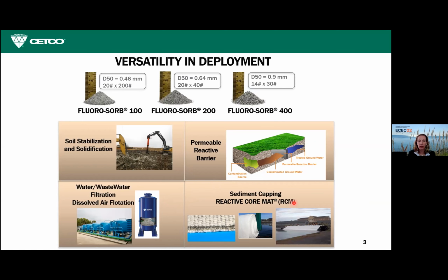And finally, really unique product, it can be made into something called a reactive core mat or an RCM. It's basically Fluorosorb sandwiched between two permeable geotextiles. It comes in these rolls that are shown here. They can be rolled out and layered upon contaminated sediment, for example, where it acts as a very thin sediment cap, so we would reduce PFAS leaching from the sediment into the waterway above. The Fluorosorb absorbs the PFAS and the water passes through the RCM.